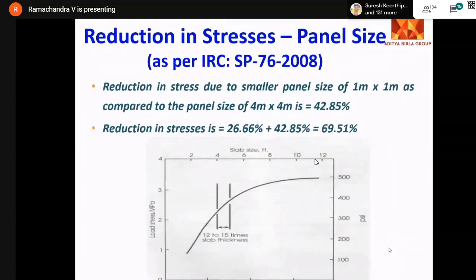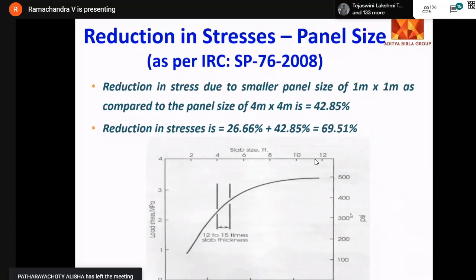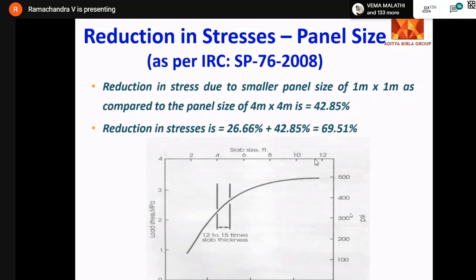Second thing is the panel size. I said normally if you take a 4 meter by 4 meter panel, compared to that, in case of 1 meter by 1 meter panel that I said we do in white topping, the stresses are reduced by 42%. Therefore, if you add these two, that means the reduction in stresses due to bonding plus the reduction due to spacing, totally it will come to 69 or even 70%. Therefore, compared to the stresses on normal concrete road of 4 meter by 4 meter, the stress reduction is 70%. That is the reason why you will have lesser thickness of white topping.